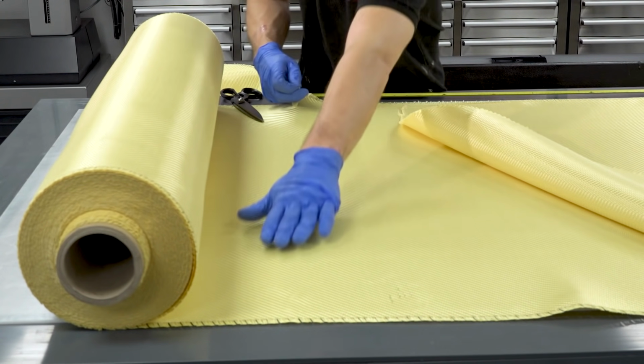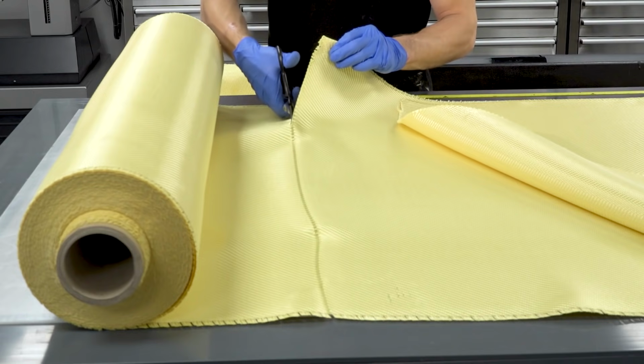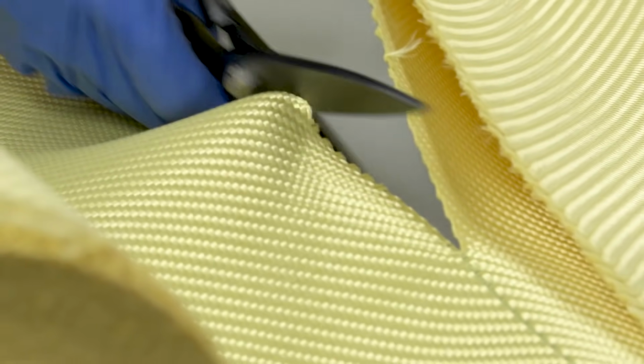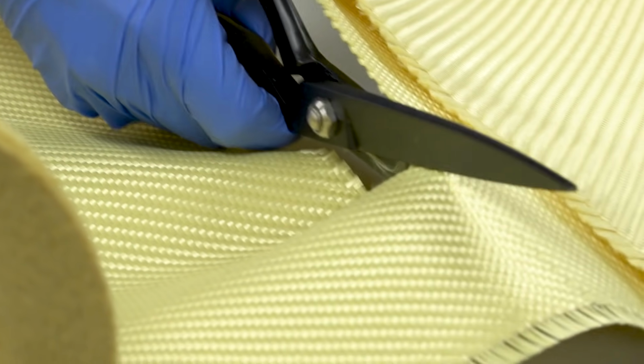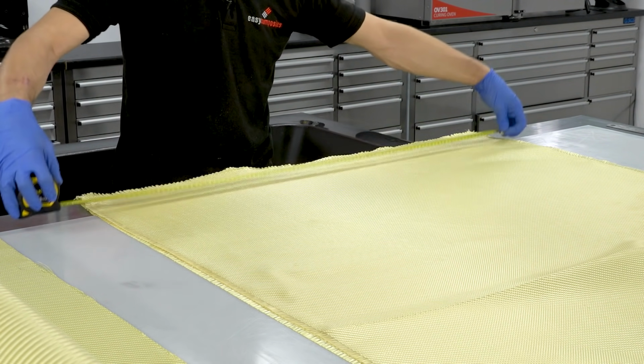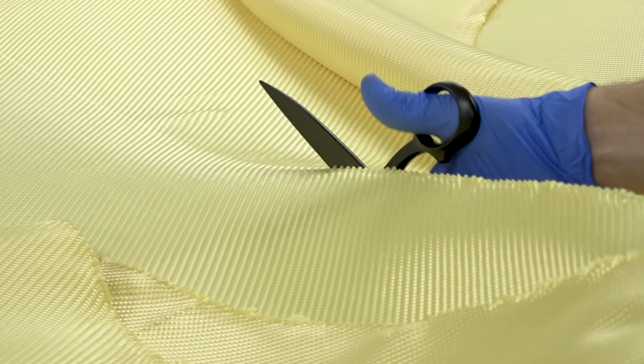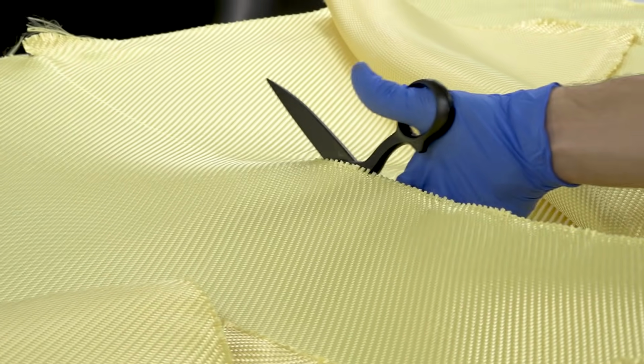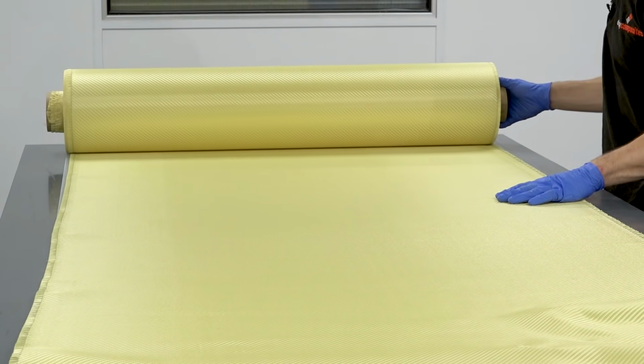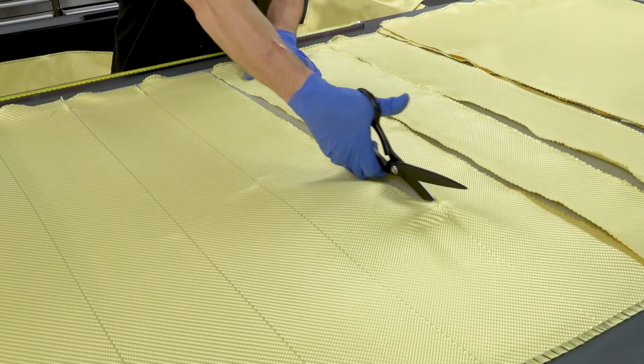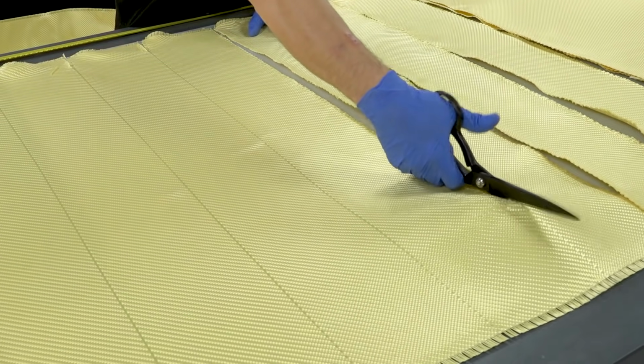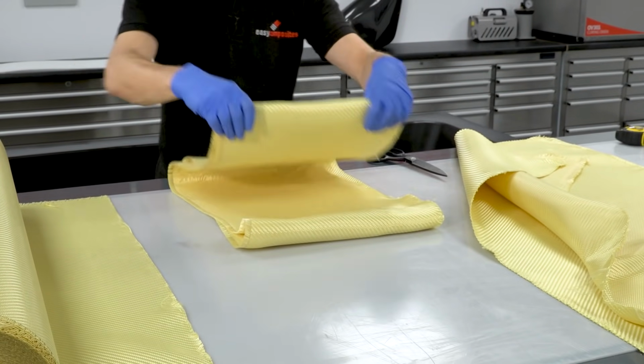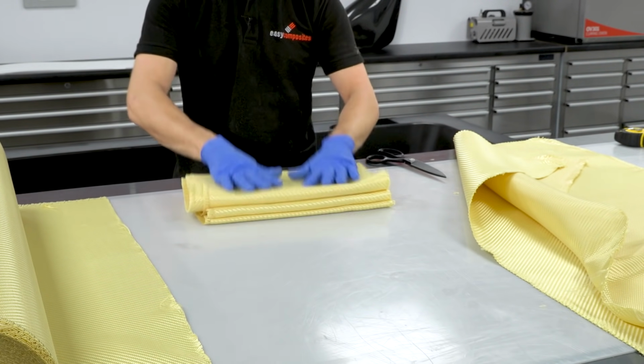Pulling a toe from the fabric gives me a quick guideline to follow with the shears. To cut Kevlar, you really have no option other than to use dedicated Kevlar shears. Conventional scissors will bind and will only make very, very slow progress. Our Kevlar shears have a specific grinding that make cutting Kevlar possible. If you do invest in Kevlar shears, reserve them only for Kevlar, as the more abrasive carbon and glass reinforcements will dull them very quickly.